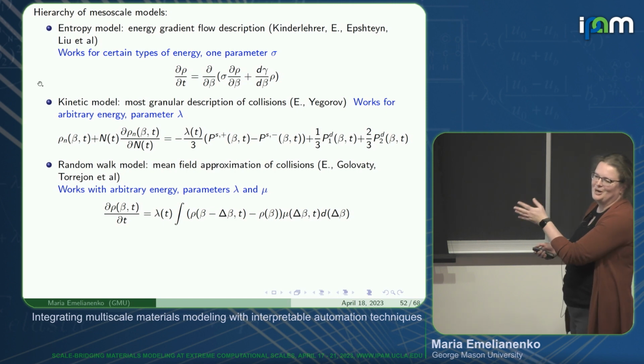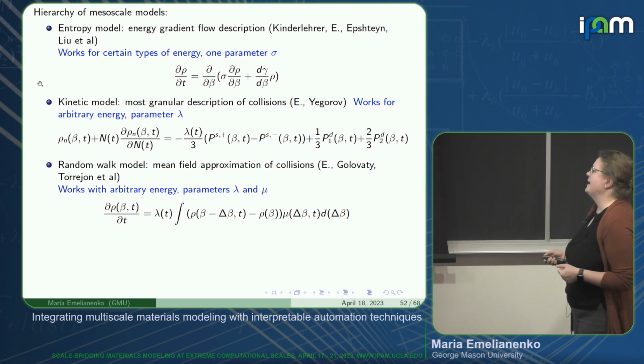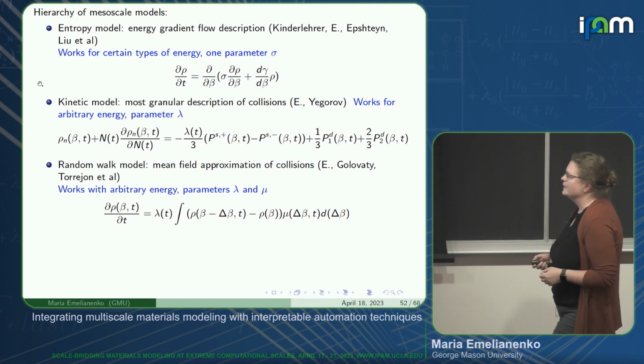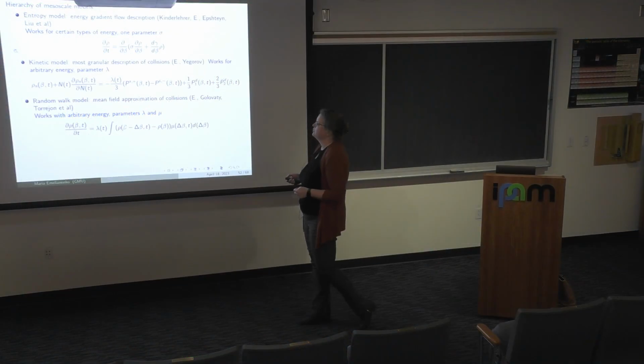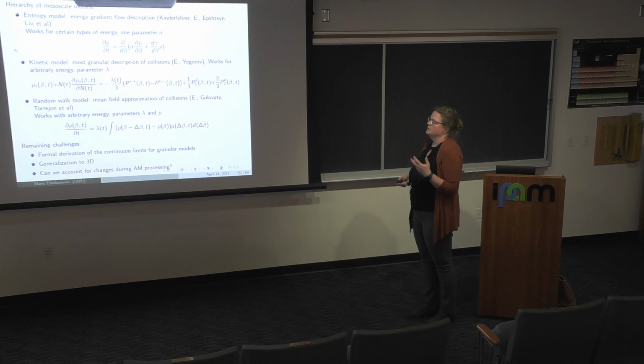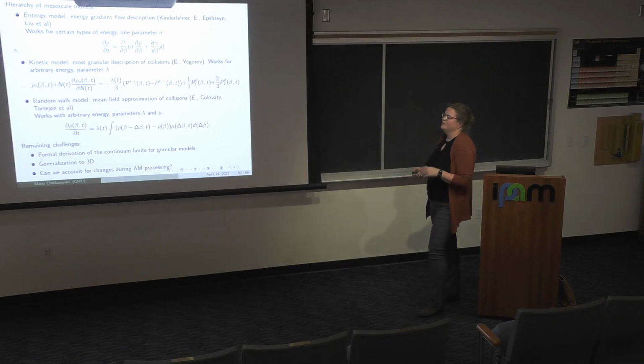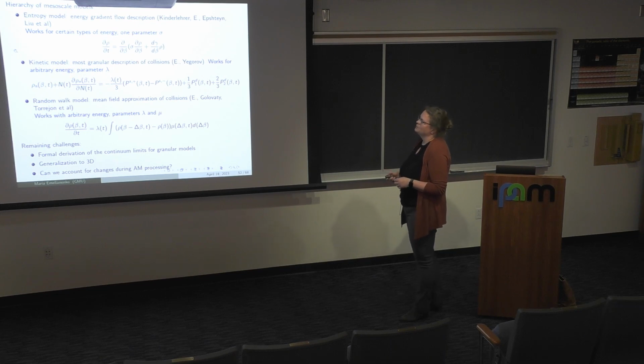So in this case, all of these collision terms do describe the specific reconfigurations that take place during the grain growth. And it's 2D, but it does handle energies that could be non-smooth, for instance. So there are a lot of integrals on the right-hand side of this equation. And we also had this random walk model, similar also to the stochastic process description that Katerina talked about. So this was another attempt to try and model the same thing. But there are still questions. So one of them is, of course, generalization to 3D, which is difficult, but I think doable, especially in this case. But also the formal derivation of the continuous limit. So how exactly these models are interconnected. That's still a very interesting question, whether or not, for instance, we can show that the equilibrium for these models match in a certain situation.